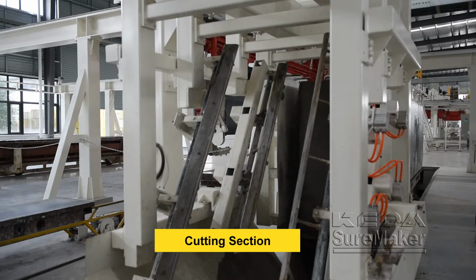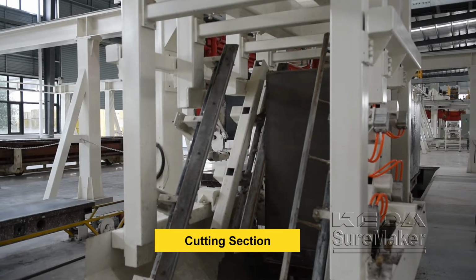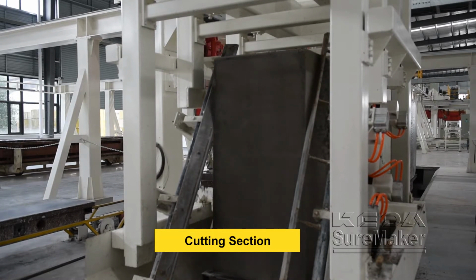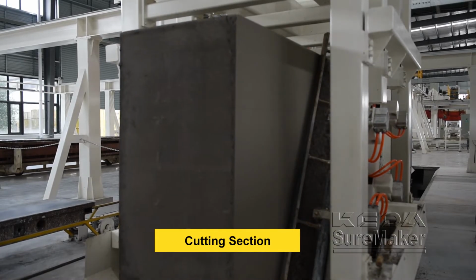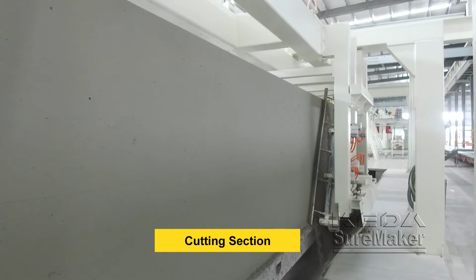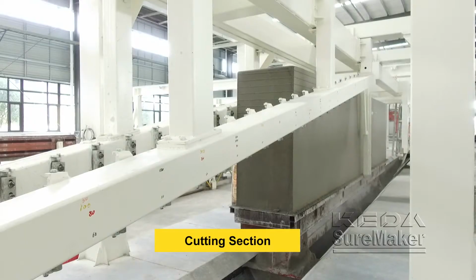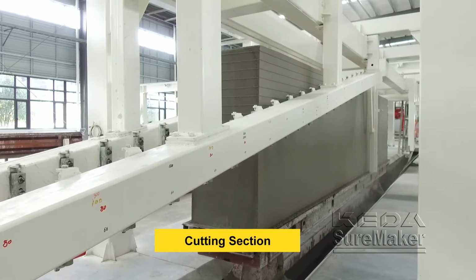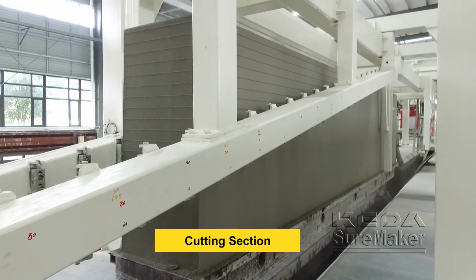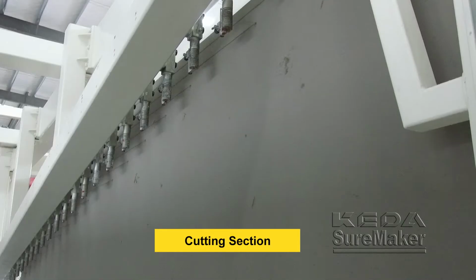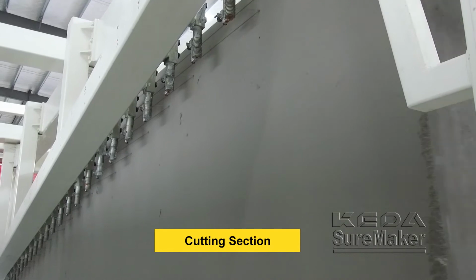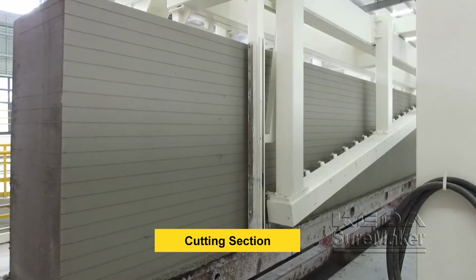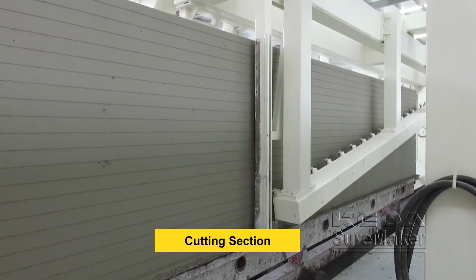The surface cutting device of the cutting machine adopts the combination of 3 steel wires and 2 scrapers to cut both side surfaces of the green cake smoothly. The cutter of the grooving machine can be changed according to the production requirement. The cable stay beam horizontal cutting machine can cut thin panel with thickness of 50 millimeters smoothly without any settlement cracks.